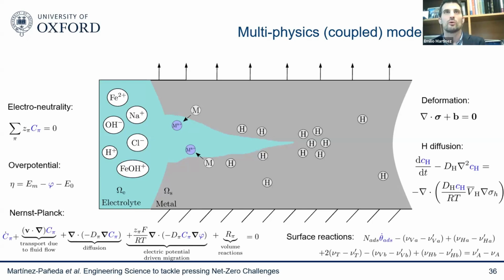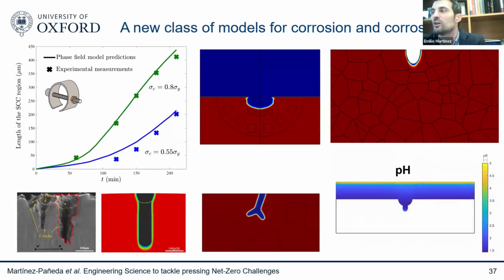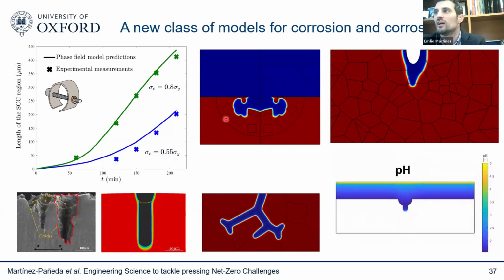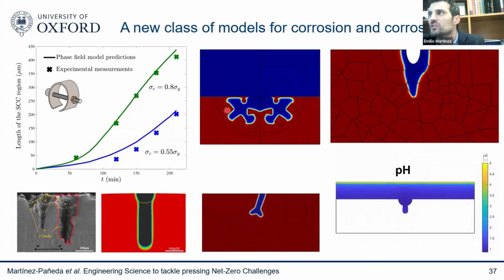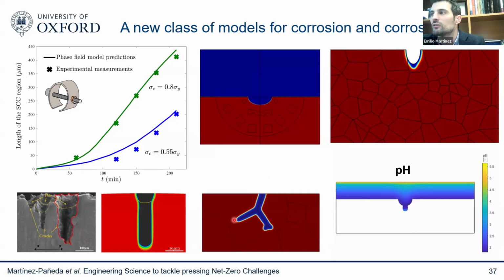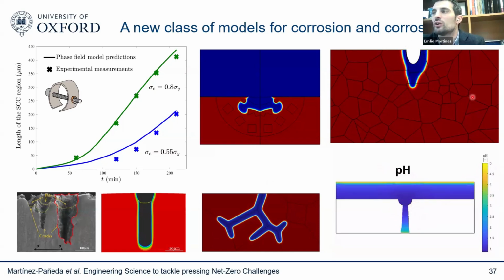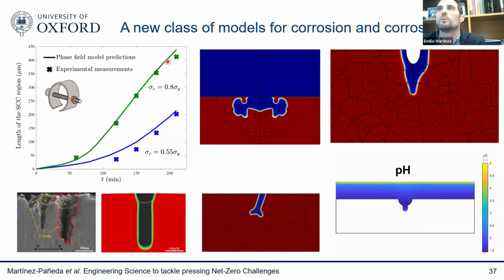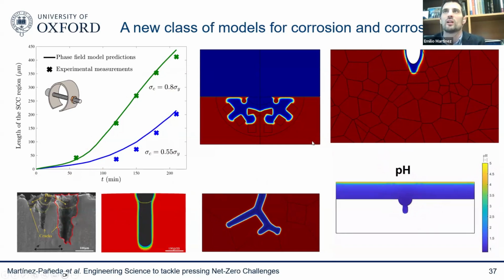And we also have, by the way, technologies to simulate how interfaces evolve. These are the so-called phase field methods. So you can see some representative examples here. We developed this new class of electrochemomechanical phase field corrosion models that allows us to predict how the corrosion front, the blue part, the seawater, evolves as a function of the metal. You can see here how the corrosion front goes across some insoluble secondary particles. You can see how the corrosion front evolves through grain boundaries. Here you can see how the electrochemistry of that corrosion front is changing as a function of the shape of your defect. Here you account for the microstructure. Again, in very good agreement with experiments, because when you bring the physics in, you get good agreement with experiments, again, both in the morphology and the degree of corrosion, and so on and so forth.